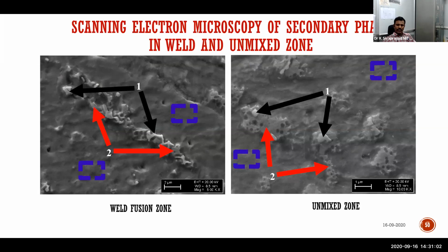The analysis associated with that, especially in the unmixed zone, shows the fineness is very disrupting in nature. If you are able to avoid this unmixed zone, probably you can avoid Laves phase. The overall summary is, if you are able to eliminate Laves phase in Inconel or Inconel-related fusion zones, you will get superior properties. That's what we have seen here.